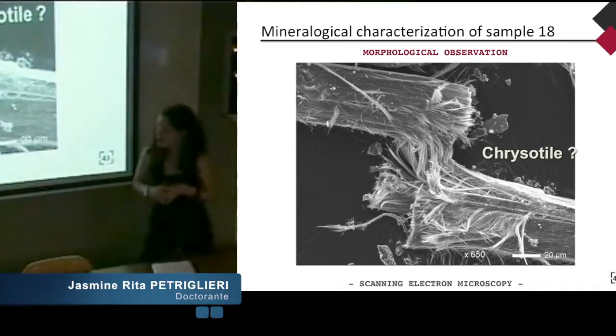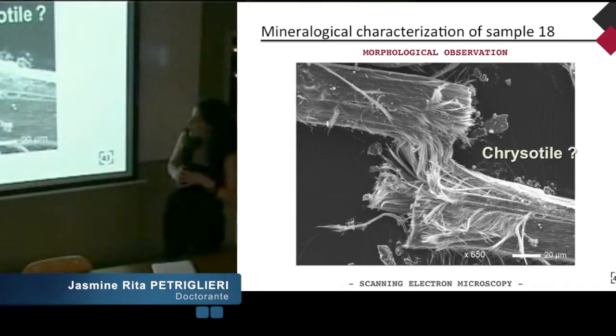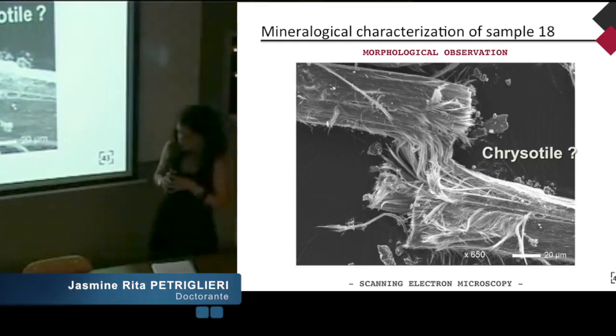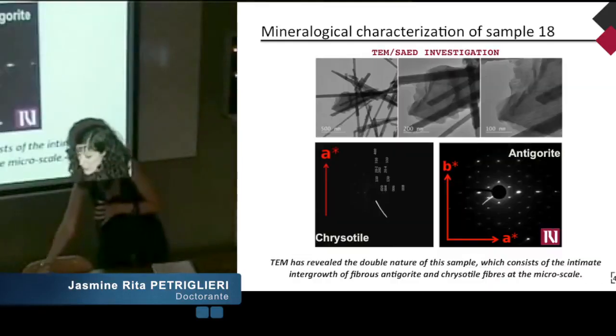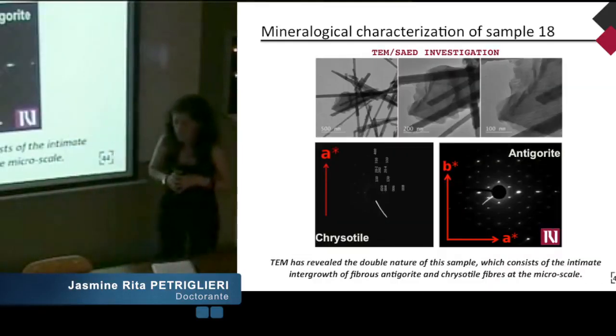So, to investigate the morphology, some images reveal a more fibrous aspect and the appearance of flexible fibers. Is this chrysotile? Finally, TEM, associated with diffraction pattern, revealed the double nature of this sample, which consists of the intimate intergrowth of fibrous antigorite and chrysotile fibers at the micro scale.